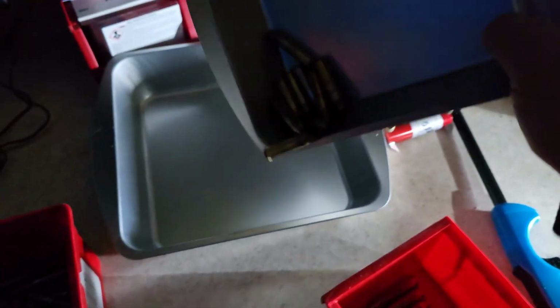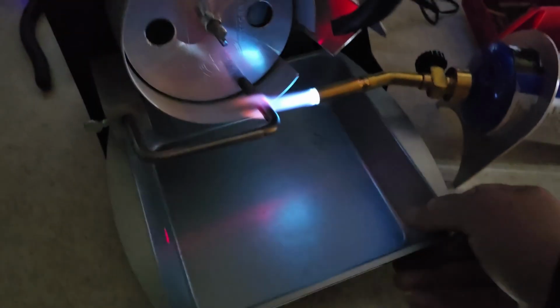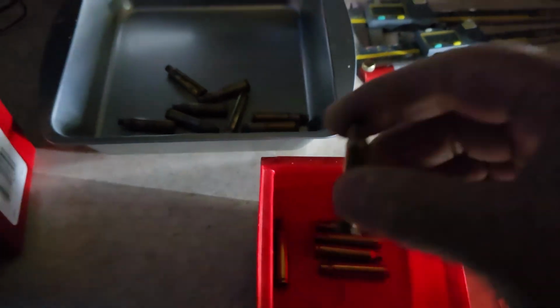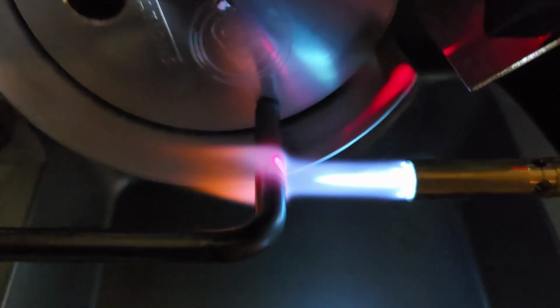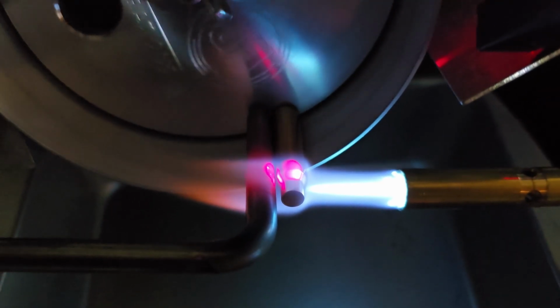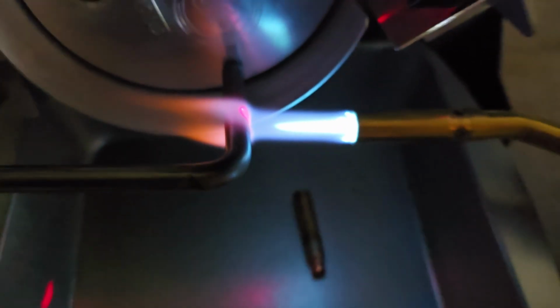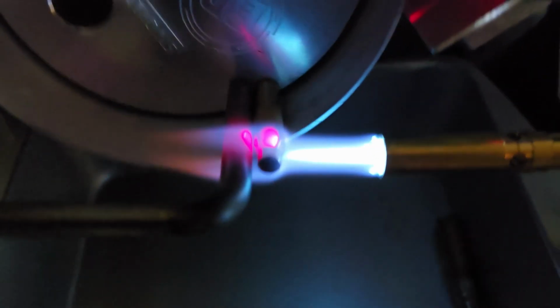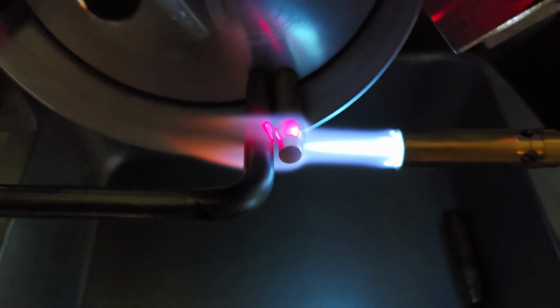And starts to glow and drops out. That's about perfect. So that's where I'm going to now take my super red hot test brass, set that to the side. I'm going to now switch over to my actual reloaded brass, and I'm going to test a couple of these pieces, and we're going to see if there's any difference. So it just starts to glow and drops out, and that's about perfect. I'm going to do one more piece, and I think we're good. And like I said, once you've done this a few times, it's super easy. You can actually see the laser from the sensor on the case, and that's about perfect.